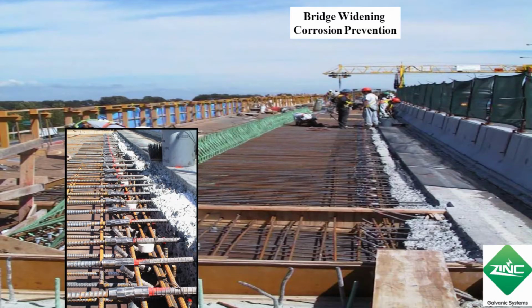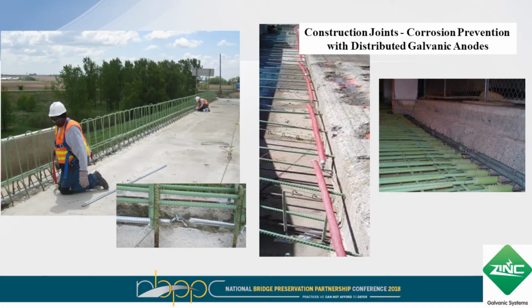So, just a photograph of a bridge structure that uses a type 1A embedded galvanic anode, localized concrete repair, galvanic anodes attached to the steel and the concrete replaced. And so the idea is that for this area, we want to make that repair last as long as we can. But these types of anodes are also used not only for concrete repairs, but in some cases for cathodic prevention or corrosion prevention. You may have situations where you have joints that are created.